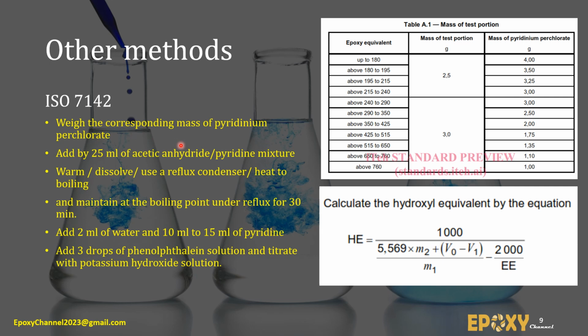So we weigh the corresponding mass of the sample, which is defined by this table. We add 25 milliliters of acetic anhydride pyridine mixture. We warm it, and we let the sample dissolve in the solution. We use a reflux condenser. We heat it to boil, and after that we let it boil for 30 minutes. After that we add 2 milliliters of water and 10 to 15 milliliters of pyridine, and add 3 drops of phenolphthalein solution and titrate with potassium hydroxide solution.